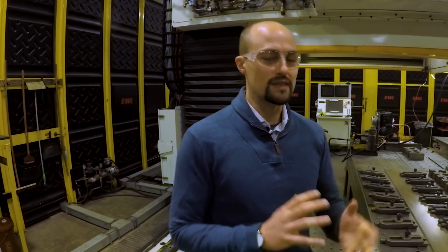Now, when we actually need those kinds of loads, we can do 3 inches thick in aluminum, so 6,000, 7,000, 2,000 series on a single pass. When we're doing that, we're only traveling maybe an inch a minute. But if you compare that to how many passes in an arc weld that would be, and the fact that with a friction stir weld we can get anywhere from 60 to 90 to 100% joint efficiencies, depending on the starting material. So how much strength knockdown do we get because of welding? With an arc weld, you're lucky to get half.